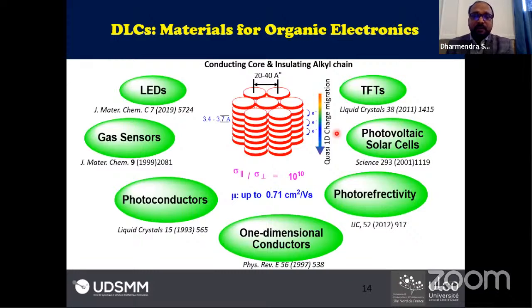So why is it important for modern organic electronics? Because due to the pi-pi stacking, these molecules can form a self-assembly in a column, and later on they can be arranged in a hexagonal matrix, rectangular matrix, and so on. The distance between two columns is around 20 to 40 angstrom, whereas the core separation along one column is around 3.5 angstrom. So basically quasi one-dimensional charge transport takes place along the column via hopping. Electrons or holes hop from one core to another core.